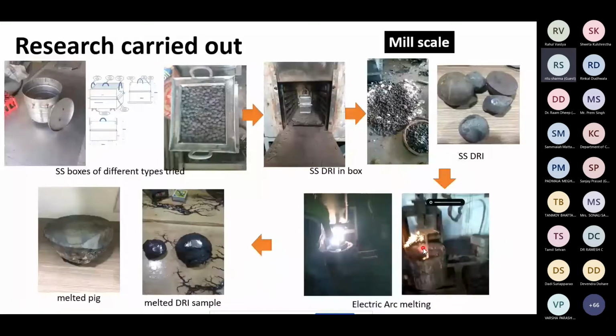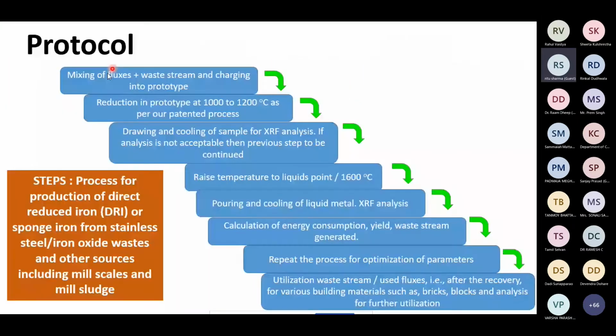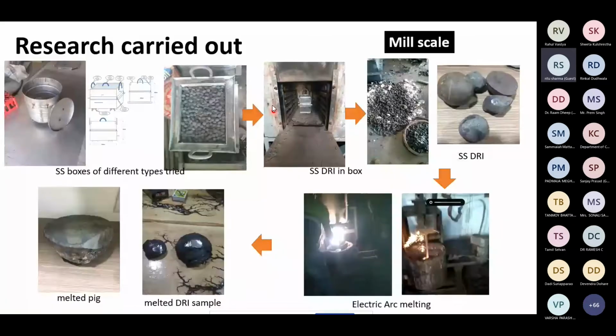This process was carried out several times. Whatever the waste material is, it is mixed with the flux, waste stream plus flux, and made into small balls. This was kept in the stainless steel box inside the furnace, taken out and cooled down, and XRF, X-ray fluorescence, analysis was carried out several times, and we identified that SSDRI, the stainless steel direct reduced iron, is produced. We put it into the electric arc furnace, a very small scale electric arc furnace, and finally melted the DRI sample into a melted pig iron.